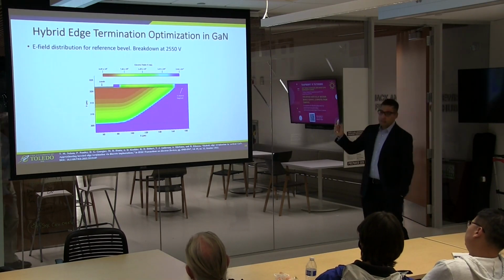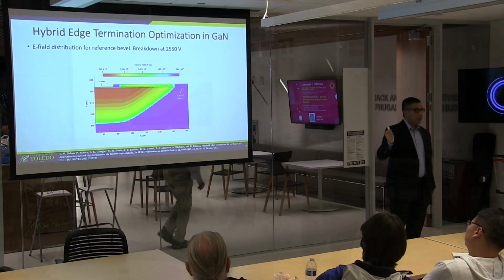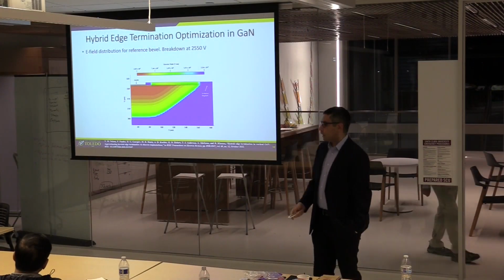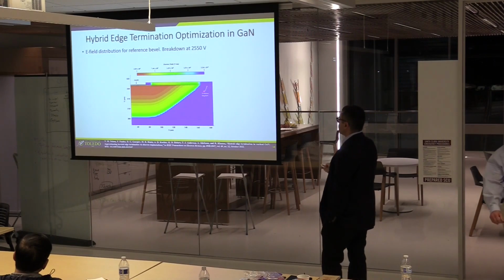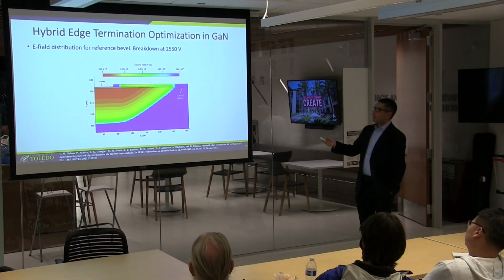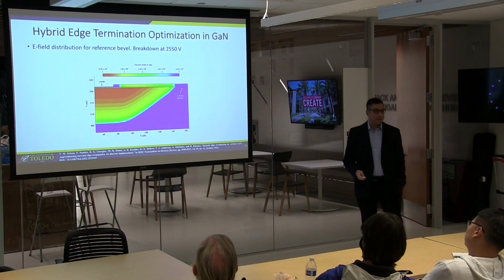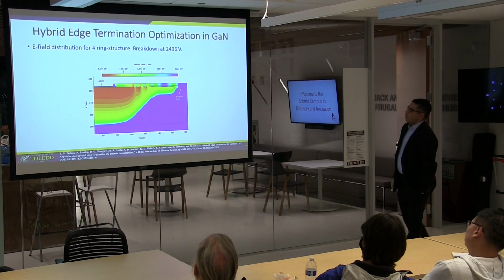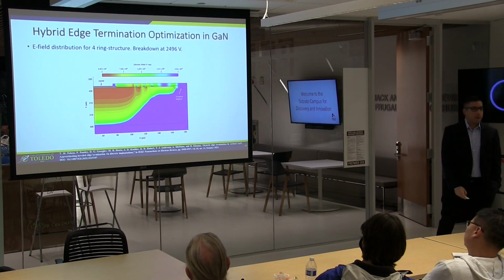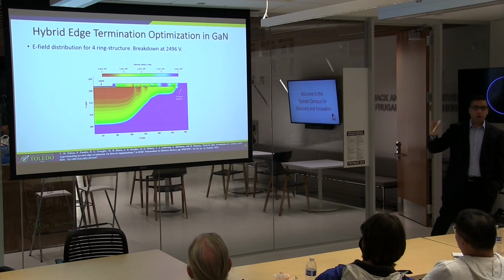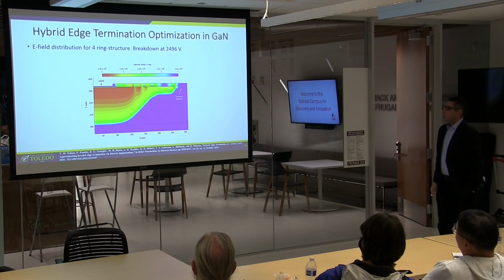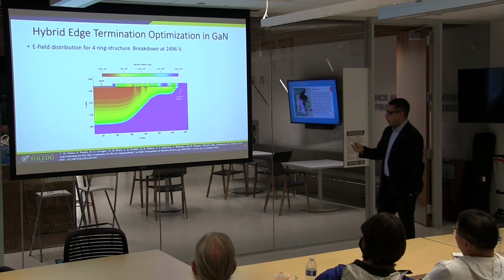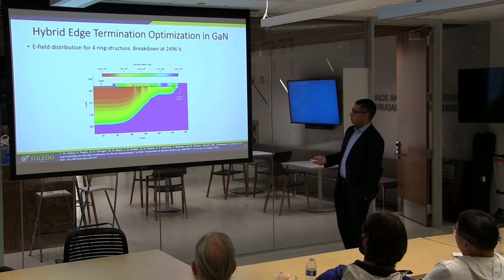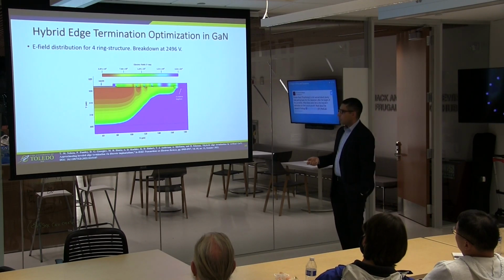So we built the older one, the bevel one, from 20, 30 years ago. We built that in TCAD. We studied its electric field distribution. You can see this one is breaking down at 2,550 volts. Then we built the 4-ring structure. Remember that previous plot I showed you. 4 and 12 had the best performance. And how do you compare them? How do you compare this with this? They kind of look alike, maybe, maybe not.